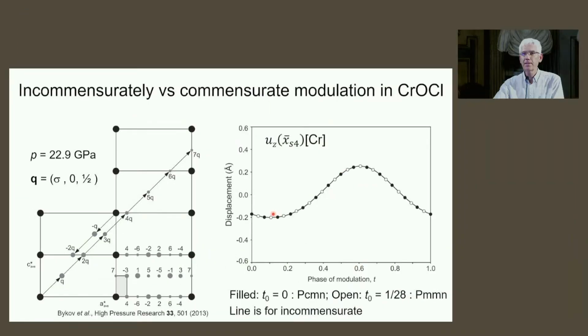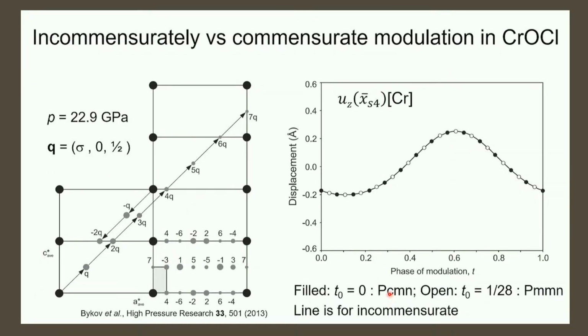If it's commensurate, we need on this line 14 points. So we can have 14 black points where we start with t equal 0, or we can have 14 open points where we start with t equal 1/28. We can also do other choices, but these are the two special choices. Suddenly we have a 14-fold supercell of orthorhombic PCMN symmetry, or a 14-fold supercell of orthorhombic PMMN symmetry, or we have an incommensurate modulation with orthorhombic superspace group.